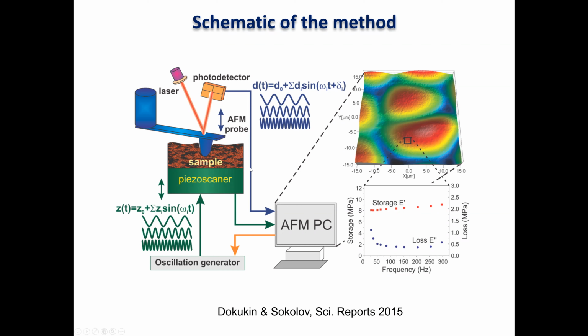So today, for example, Bruker's AFM-nanoDMA measures a single frequency at a time. We suggest measuring multiple frequencies at a time because it gives you two advantages. One is a more or less obvious increase in speed, because you process several frequencies at the same time. But secondly, it allows us to do the measurements so quickly that we don't need to wait until creep relaxation or stabilization of the contact. That is one of the most time-consuming parts of previously developed nanoindentation.